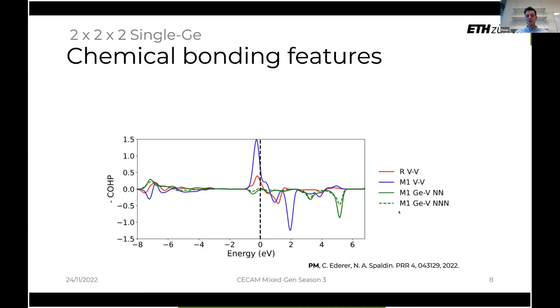And we pursue this further by looking at the chemical bonding that occurs between this added germanium and the vanadiums around it. And in particular, what we look at is something called COHP, which is the crystal orbital Hamiltonian population. And in my view, it can be looked at as a directional density of states. In some sense, if it is positive, it tells us that there is a bonding feature, whereas if it's negative, it tells us that there is an anti-bonding feature.